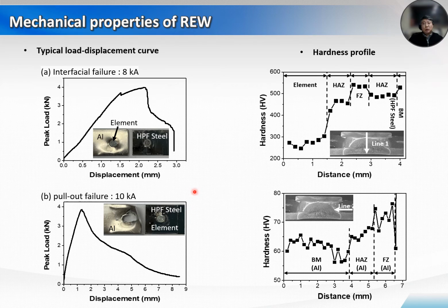By confirming the joint strength and fracture mode of this welded joint, we derive the optimal condition for securing a high-quality welded joint when applying aluminum damping plates to the one-step resistance element welding process. If a larger, higher-grade thickness of aluminum is applied, then this result may differ, and the pull-out failure load will be much higher than under this condition.